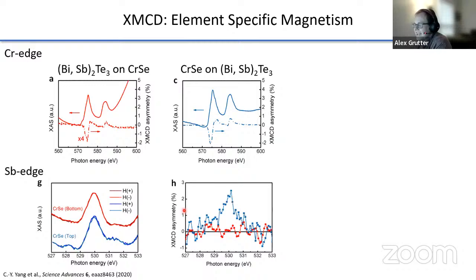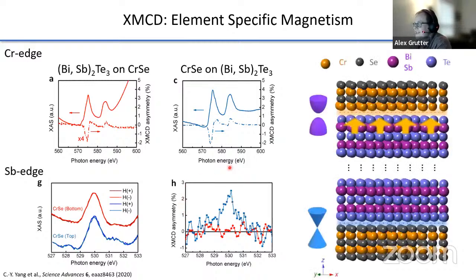So how do we understand this? Well, density functional theory calculations actually tell us that the order should matter. The chromium selenide termination is strongly dependent on the growth order. If you grow chromium selenide on top, it's going to grow chrome terminated, which means that the chrome moments are right up in contact with the bismuth antimony telluride. And actually, you also expect a slightly larger interface moment in the chromium. And those two combine to open up a gap and give you a net magnetization.